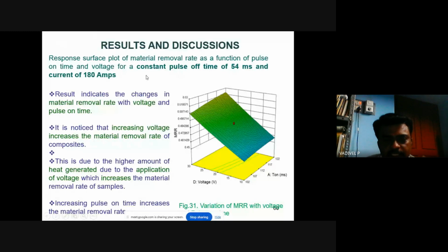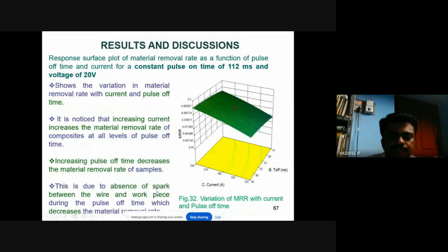This chart is for 54 ms and 180 amps of current. You can also see that when we increase the voltage, the metal removal rate increases. Application of voltage increases the metal removal rate of the samples. The next plot is with 112 ms and voltage of 20 volts.